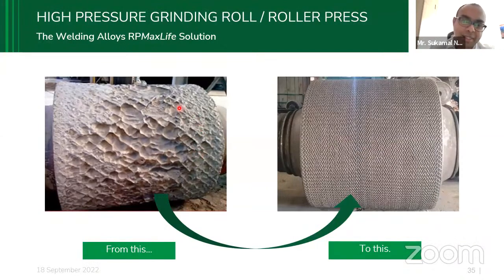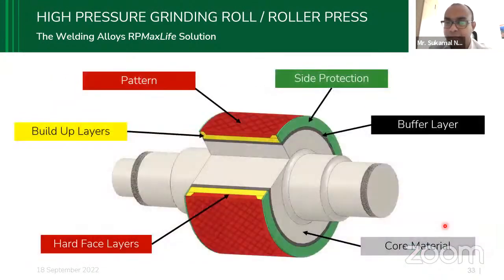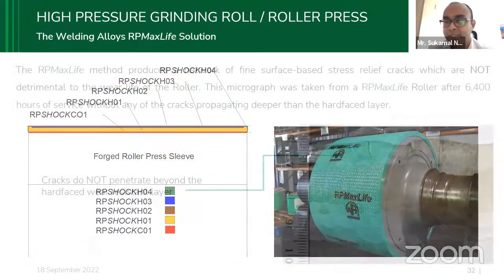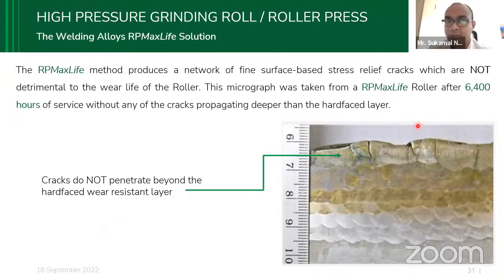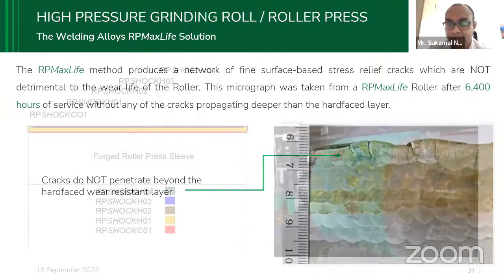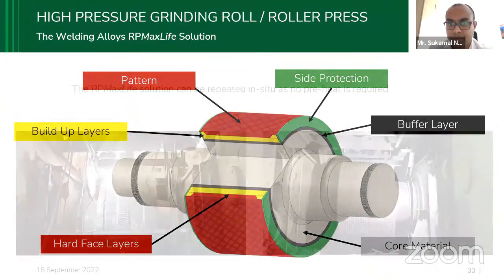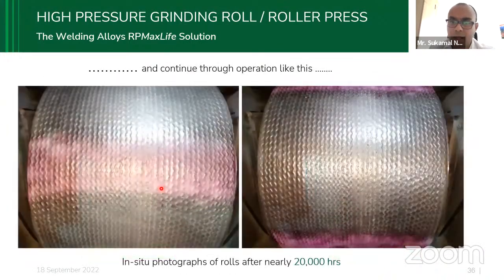This is quite interesting. You can see how this roller looks, and during COVID we took it from a scrapyard and rebuilt it, and it actually enhanced the life. From the previous slide, as I showed you, around 6,400 hours, it has increased the life here. That's a tremendous increase in life. This is an in situ photograph after using it for 20,000 hours, how it looks. So we can see that we can use it.